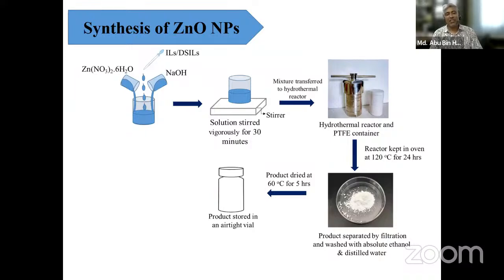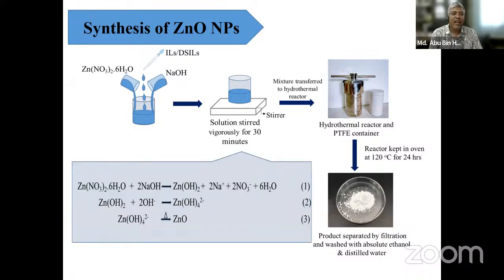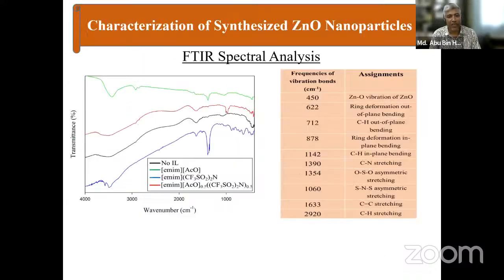So the synthesis is exactly similar. We have the precursor here, zinc nitrate, and for ionic liquids, we have used double salt ionic liquids and sodium hydroxide. These are all common, with a hydrothermal reactor and Teflon container, and here the temperature has been set to 120 degrees centigrade. After drying the product at 60 degrees centigrade for 5 hours, we could have our product separated. The reaction scheme is also exactly similar to that previously reported for the single ionic liquid.